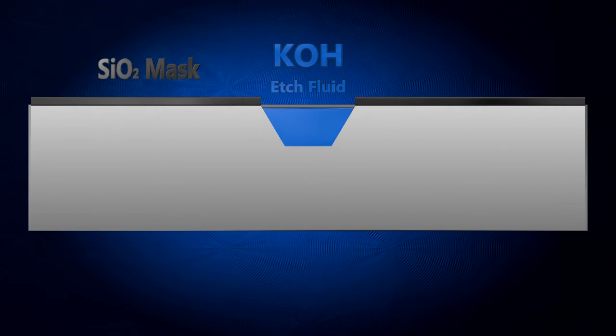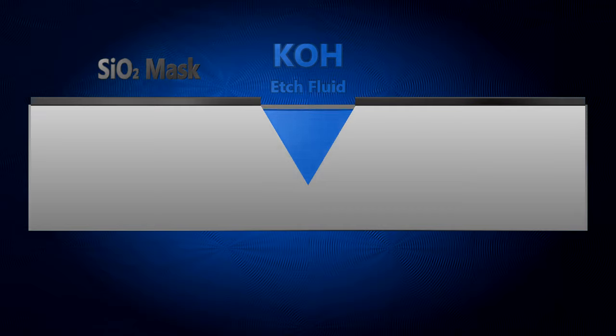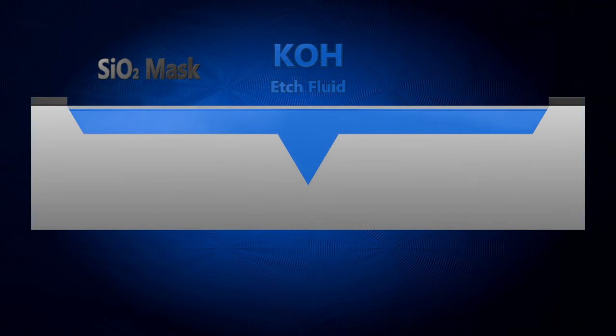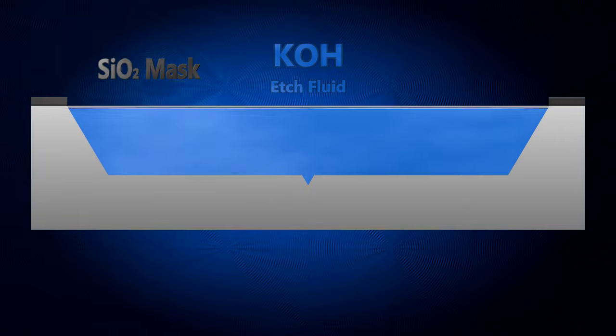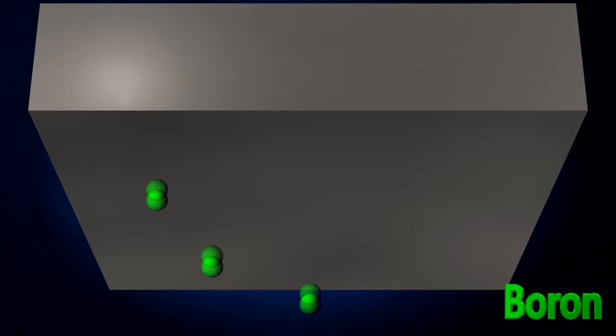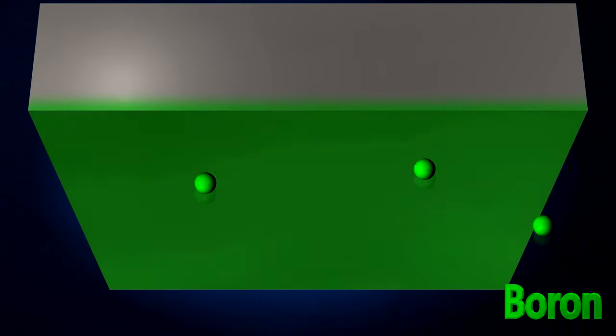Likewise, we can apply masks to materials to affect a change in only the area that we want. So if we make a mask like this out of a material that is resistant to the potassium hydroxide etch, then we can control how large a pyramid shape is and by controlling how long we allow it to etch, we may stop it at any depth. Or if we wanted the etch to stop by itself, we can bombard only this side of the silicon wafer with boron atoms to some precisely controlled depth into the material. By making that area of the crystal impure, the etch will stop once it reaches it.